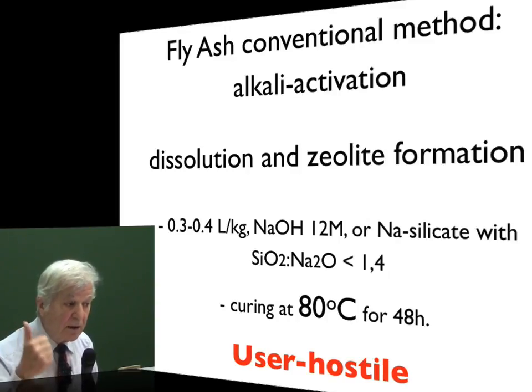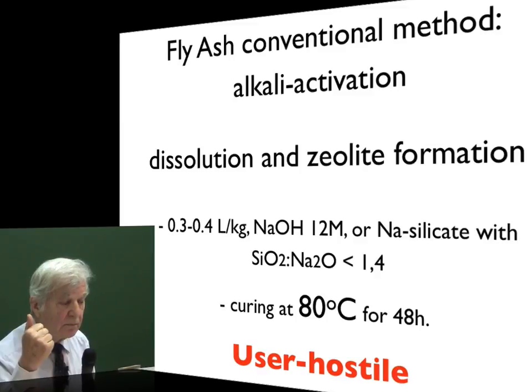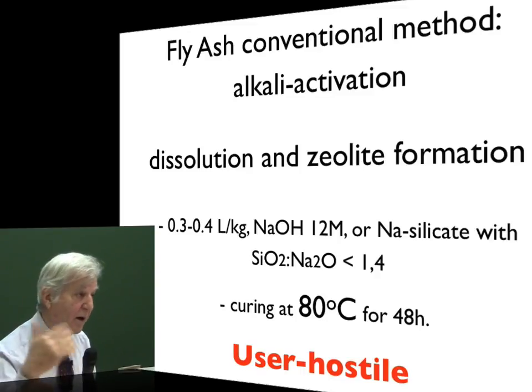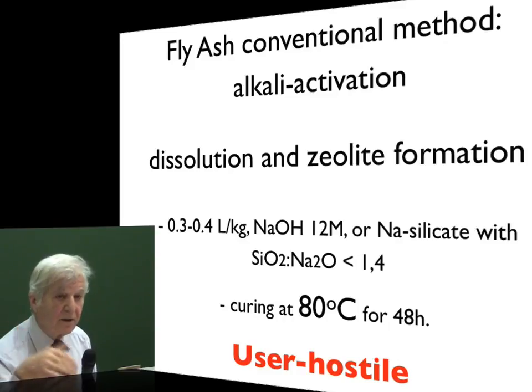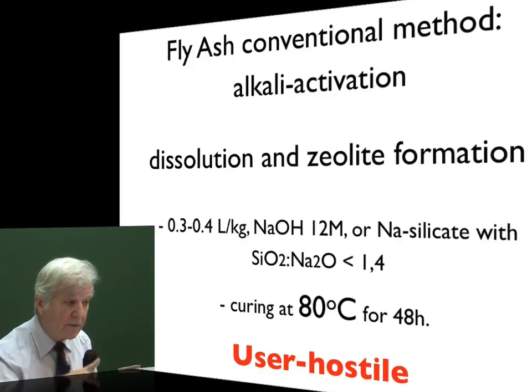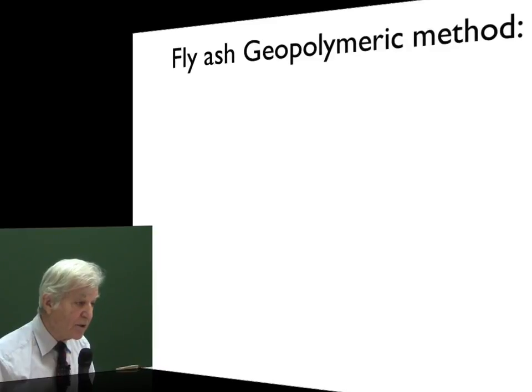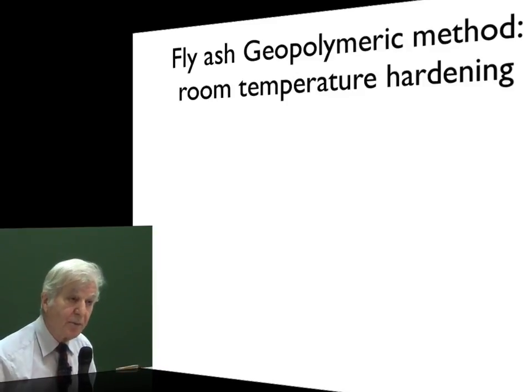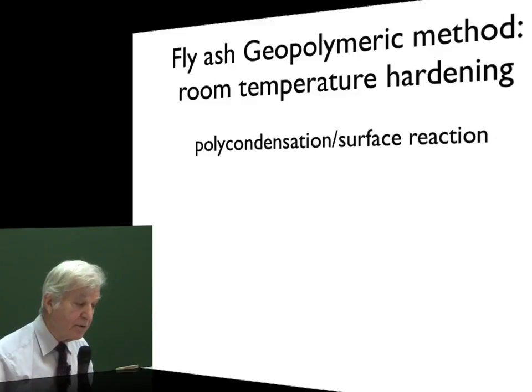First, we are dealing with a cement. A cement is a room temperature hardening system. If it requires temperature for hardening, it is no longer a cement. It is something else. They said, okay, it's fine for precasting, but it is not a cement. So forget about that system. The fly ash geopolymer method is room temperature hardening. Polycondensation, we react on the surface of the fly ash. We don't dissolve the fly ash. We just need a very small amount.